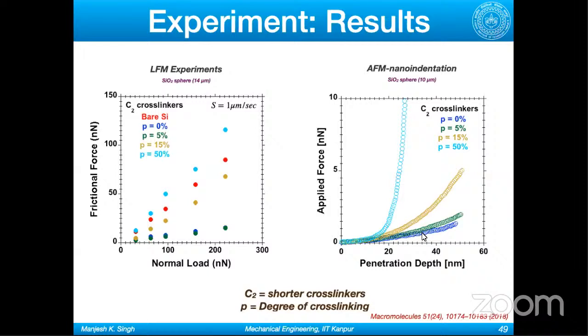So how can I tell you this? This change in slope, which you can see on your screen, basically tells you that the silica sphere is already feeling the substrate. This sudden change in slope indicates that the silica sphere feels the silicon wafer substrate on the surface. So it tells you that as you increase the degree of cross-linking, the swelling of the polymer gels is going down. That's why it can feel the substrate very early.